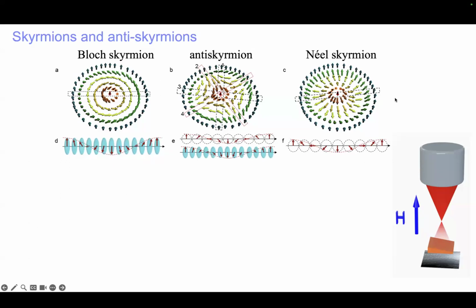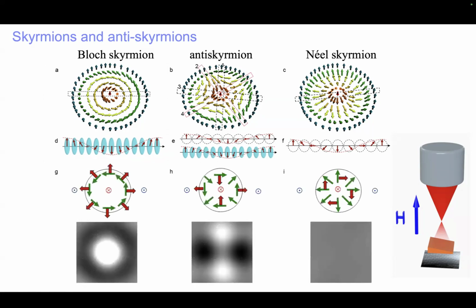In our case, we have a 300,000 volt electron beam that's passed through this device, and this magnetic material will scatter the electrons to the left or right, depending upon the component of magnetization in the plane of this structure, which is perpendicular to the electron beam. And then we can actually calculate what we would expect to see.